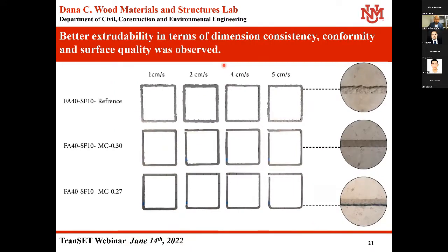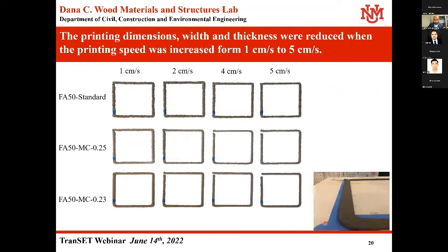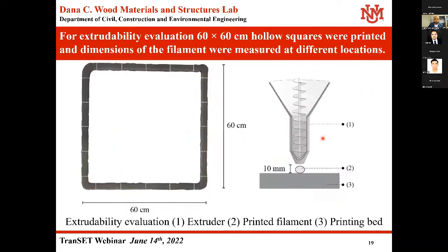Also, with the addition of viscosity modifier in the mix, the extrudability was considerably improved in terms of dimension consistency, conformity, and surface quality was also very good as compared to the standard ECC mix without any viscosity modifier.